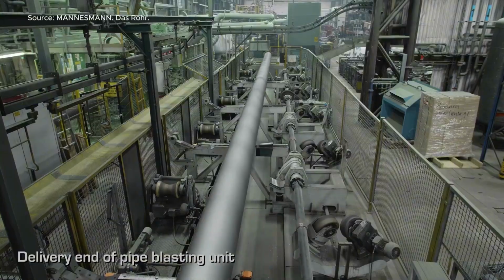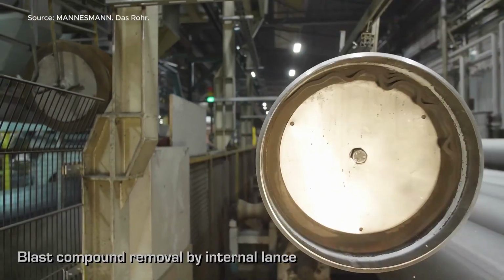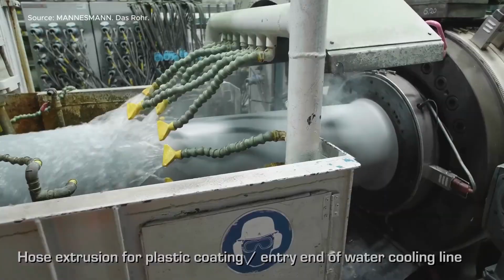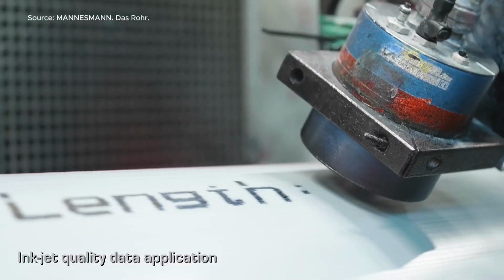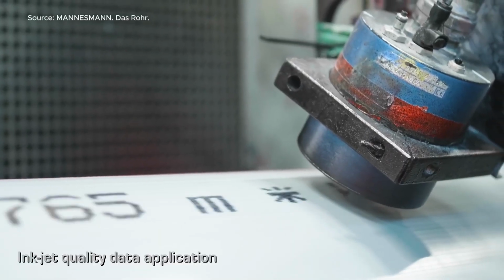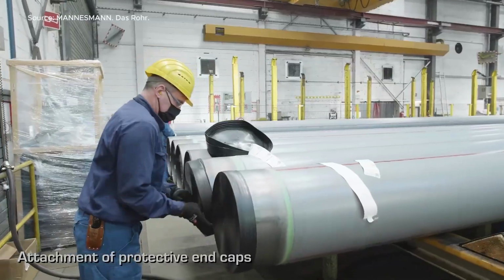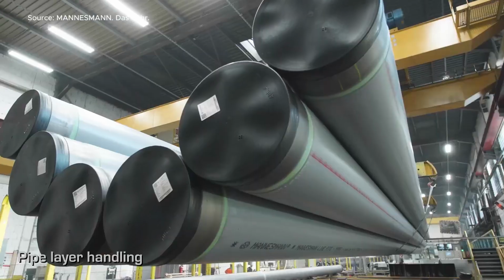Pipes, ranging from 114.3 mm to 508 mm in diameter and 4 mm to 20.6 mm in thickness, are tested for pressure resistance, ensuring their integrity for applications like oil and gas transmission.